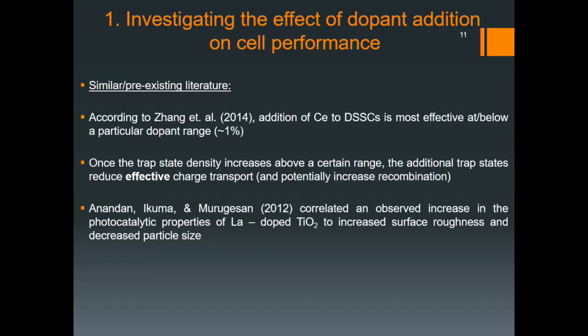Now, existing literature does state that based on the dopant range that we chose, lanthanum elements will have different ranges for ideal performance. Cerium, in particular, tends to reduce efficiency above 1%. And we were doping between 0.25 and 5% throughout our dopant study. All right? Even when we went down to a dopant level of 2%, that's still relatively high. And that could explain the reduction in performance that we saw.